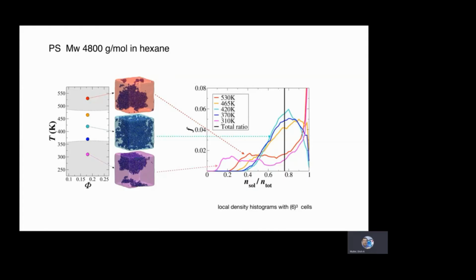We performed very large simulations for these systems, and it was also a challenge to try to understand what is a phase-separated system and what is not. A nice way of studying this is by looking at local density histograms. So in the blue figure in the middle, the question is if this is a one-phase or a two-phase system. By looking at the density histograms, you can see that there is a mean histogram size, and there's some spread around this mean, but in general, there's only one histogram distribution.